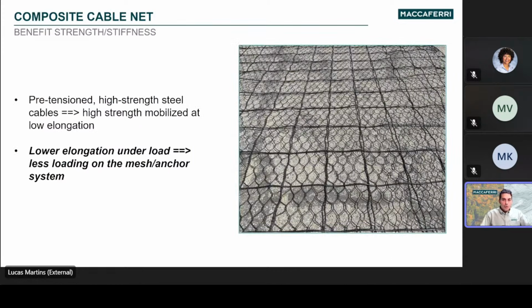That brings us to our cable net, or our composite cable net. The system incorporates a net or a grid of pre-tensioned high-strength steel cables that provides very high strength, with a peak strength mobilized under very low elongation. Those cables are inserted into the mesh under tension, so as soon as you tug on them, they're going to tug back.